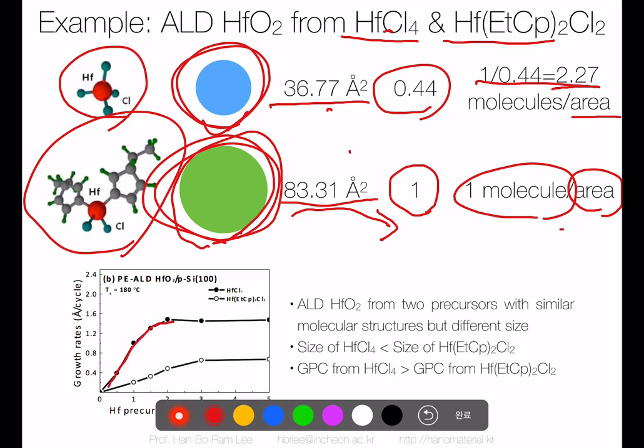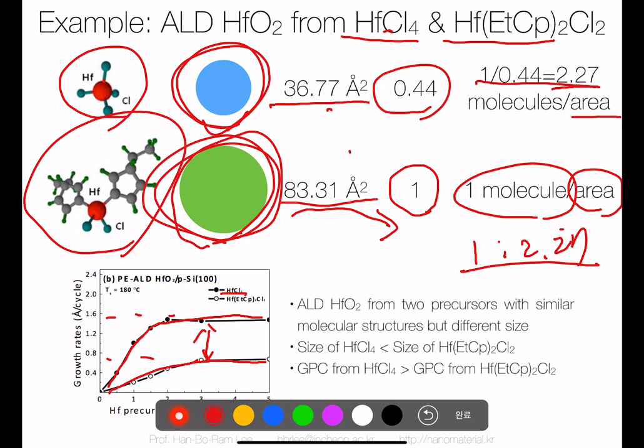This is the growth rate. So this is the hafnium tetrachloride growth rate. This is the hafnium ethyl cyclopentadiene chloride growth rate. Interestingly, this is much larger than this. We expected that, and the ratio is exactly the same as 1 to 2.27. Well, definitely we have done the calculation of the reactivity between these two different precursors, so we have to make sure the reactivity does not affect the steric hindrance. But interestingly, our very simple calculation matches very well with our experimental result. So this is one strong example for